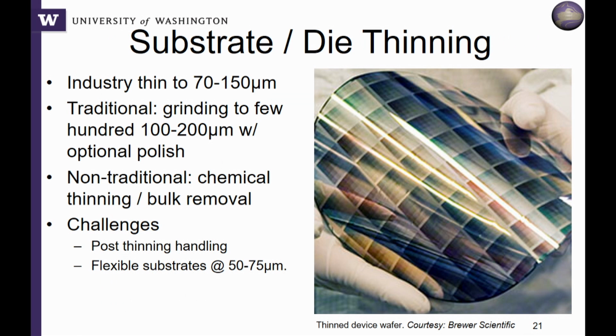So we can thin those down. Our industry is getting really good at thinning components, so the chips themselves are thin now, somewhere between 70 and 150 microns, but we were proposing to also thin the carrier itself.